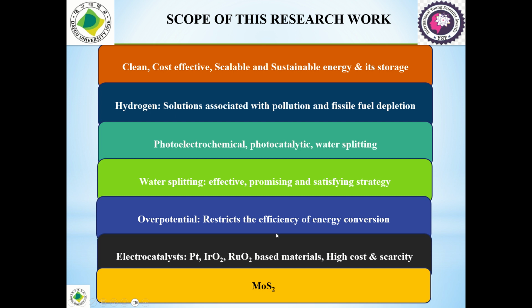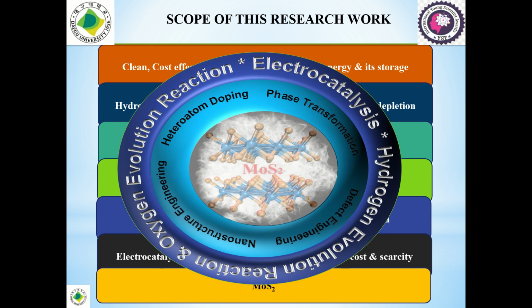Up to now, platinum, iridium, and ruthenium based materials are the most usable, however their high cost and scarcity affect large production. So we chose MoS2 to replace these very expensive materials. MoS2 in the pristine structure cannot give the best performance as an electrocatalyst. So we chose different types of techniques to modify it, like phase transformation, heteroatom doping, nanostructure engineering, defect engineering, and so on.